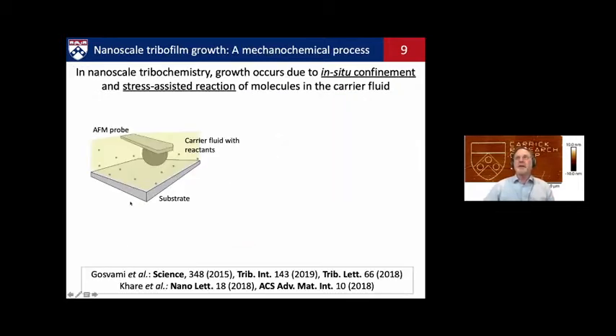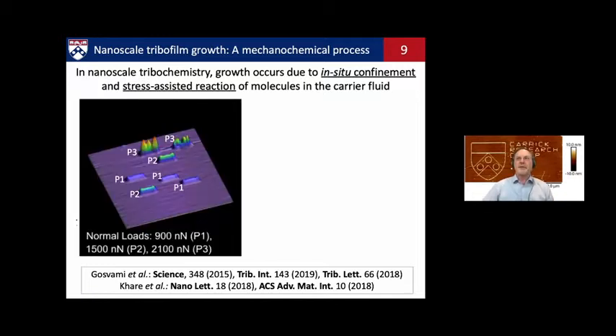So it's just a cartoon illustration. If you slide several times, these molecules are being trapped in the contact. They're experiencing these compression and shear forces. They're reacting with each other, and they build up these films. So tribological stresses are assisting the chemical reactions to drive the growth of these tribofilms. And here's just an example of playing around. Here at a load P1, you get some film building up. Here, a higher load, but same number of cycles, a thicker film, even thicker film at a higher load P3. So you can essentially dial in and draw these tribofilms where you want them.